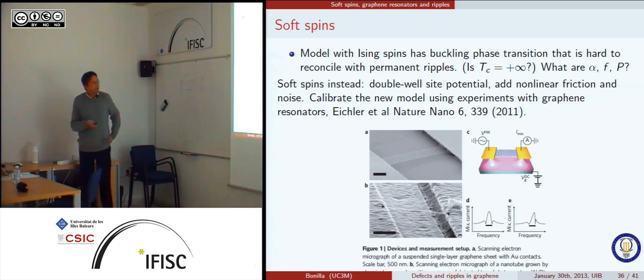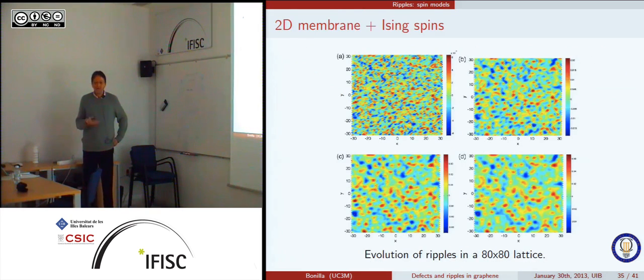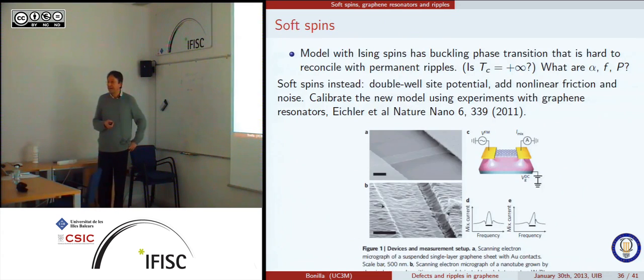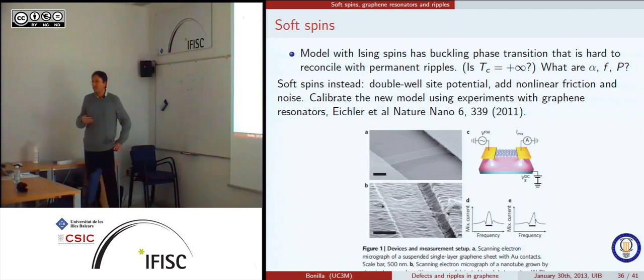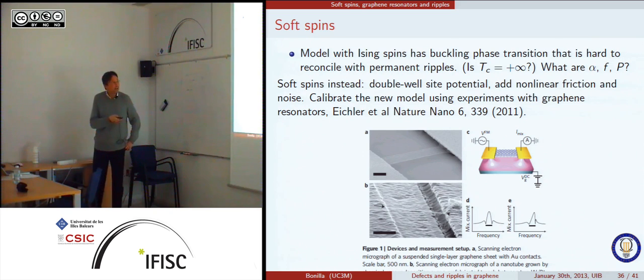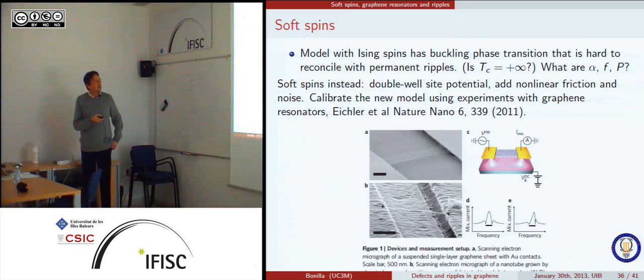Okay, so this model has, among many other defects, the defect that the spins are all invented. We do not know what the coupling constant is between these invented spins and the atoms or anything like that. So we look for a different set of experiments to see whether we would be able to calibrate these parameters with experiments. We found that there are many experiments with graphene resonators in which you just take two contacts, put